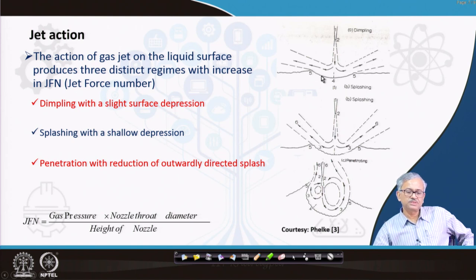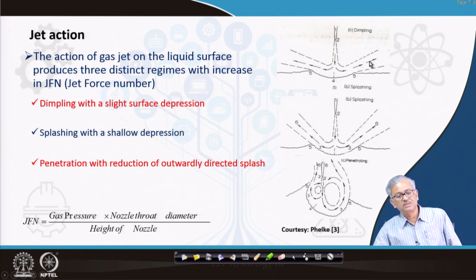In the case of dimpling, the surface depression is very small. In splashing, the surface depression is much higher compared to dimpling. And in penetration, they form a big crater on the surface. The liquid droplets are ejected away in this way. Here the droplets are ejected at a very small angle to the horizontal, and they can directly hit the refractory wall. In the other case they move a little off, go through the slag phase and may be damped there.